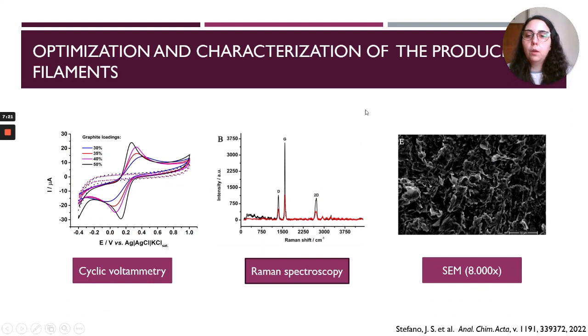So first of all, we have optimized the composition of the filament and characterized it. Here on the left, you can see some cyclic voltammetries using ferrocyanide as a redox probe with different graphite loadings. As the graphite loading increases, we have lower peak separation and also higher peak current. But the problem is, if you enhance the graphite loading too much, you will have a brittle filament.